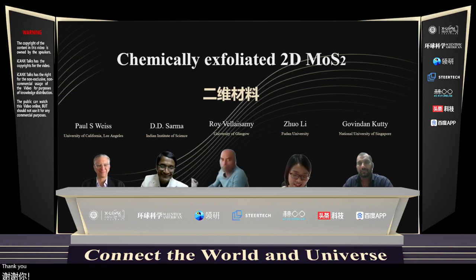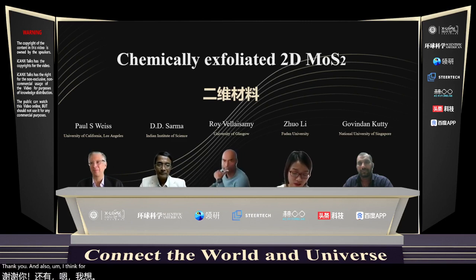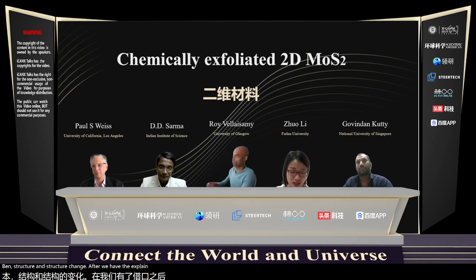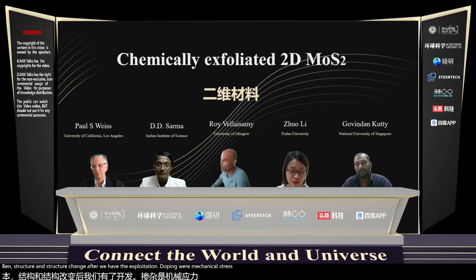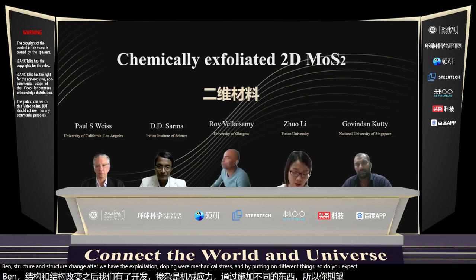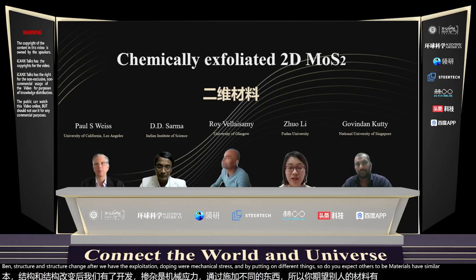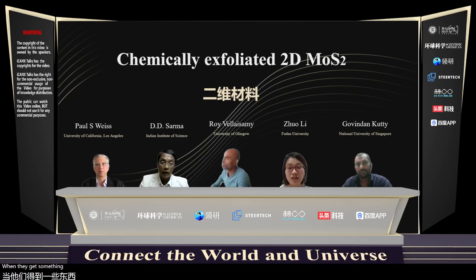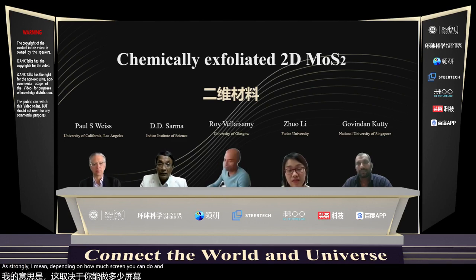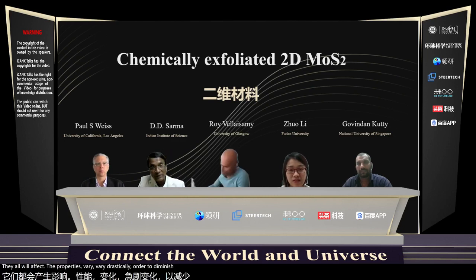Okay, thank you. And also, I think for MoS2, we see the band structure and structure change after we have the exfoliation, doping, or mechanical stress by putting on different things. So do you expect that other 2D materials have similar behavior like MoS2 when they get so thin? Absolutely. I mean, strain certainly would affect the electronic structure strongly, depending on how much strain you can give. And if you are able to dope or if you are creating defects, they all will affect the properties very, very drastically, other 2D materials as well.